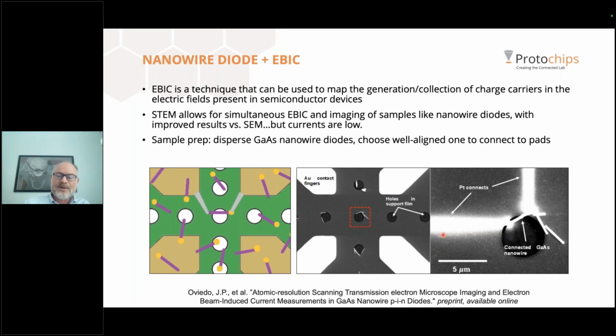That's a really powerful technique if you're trying to scale devices. The smaller probe size of STEM over SEM allows for better localization of these fields, albeit with a lower current. So here, the customer started by dispersing a set of these nanowire diodes across the surface of the electrical chip.